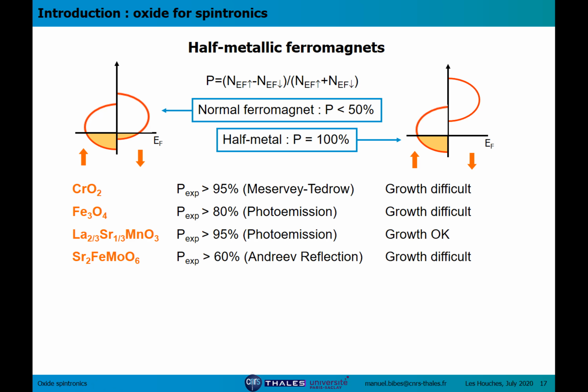As I've shown you, most transition metal ferromagnets have spin polarization that does not exceed about 50%, but oxides are interesting because there's a number of compounds in which this spin polarization can be much higher. This is a list of such compounds: chromium oxides, Fe3O4, which is magnetite, manganites, in particular LSMO, and double perovskites. There are some other compounds, but these are the most important, I think.